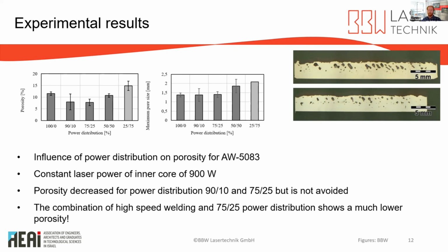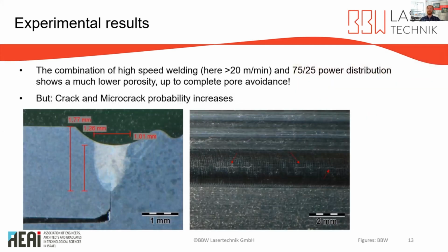The porosity can be improved further, and we must do this also by combining with other strategies. For example, high-speed welding. And this is what we can check here. We went here into a very high-speed welding profile. We have used here a welding speed of 26 meters per minute and the power distribution of 75 to 25% with the 2-in-1 fiber. So we enable here almost no